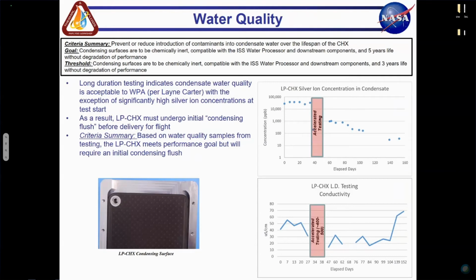Our big test objectives were 1, to look at our water quality, 2, to look at our micro and fungal growth, and 3, to look at our heat transfer and compare it to the model. So the results, in terms of our water quality, we got water quality samples about once every other week for the duration of the test. Our criteria summary for this was to prevent or reduce introduction of contaminants into the condensate water over the lifespan. In that lifespan, our goal would be 5 years. Our threshold would be 3 years.